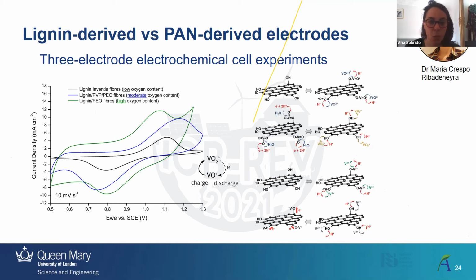So here, these are all our fibers, right? But we tuned the amount of oxygen groups that we had. So these have a low amount, a high amount, and this is even higher. We can see the current density is higher when we have a higher number of oxygen groups, and also that the potential shifts to slightly lower values.